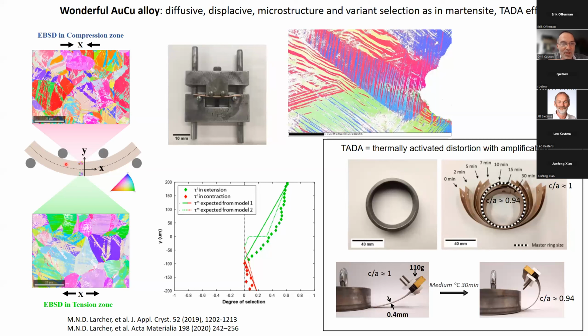Here is the contraction part of the bending sample, and we have the c-axis parallel to the x. And here, it's the reverse. That's why we have a change of color. So it was a kind of proof that even if it's an order-disorder diffusive transformation, it is also a displacive transformation. And if we look by TKD, we can see that we have a lath inside a lath. It's a fractal representation, exactly as in a lot of shape memory alloys.